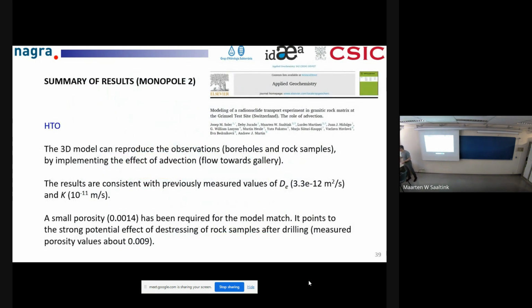Right, so, a summary of the results. By the way, this is published this year, 2024, so the details can be found in there if you're interested. Summary for tritium: we did a 3D model to reproduce the observations, both borehole concentrations and the concentrations in the rock samples. We needed the 3D to be able to implement the effect of advection. We have this flow in a direction more or less parallel to the boreholes going into the gallery. The results are consistent with previously measured values of diffusion coefficients and hydraulic conductivities.